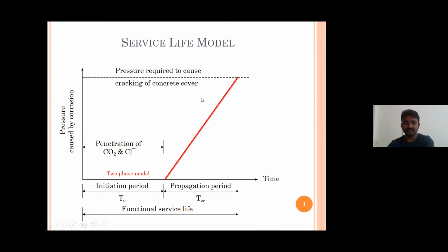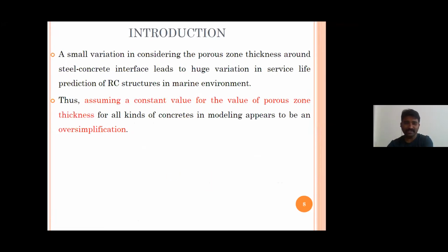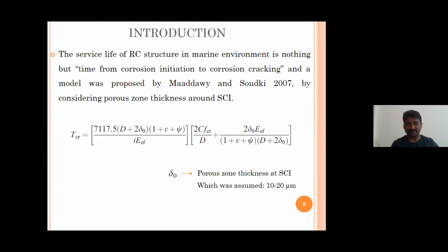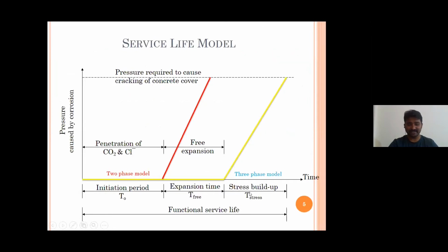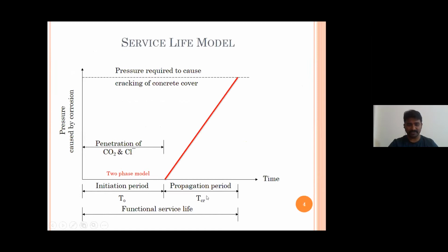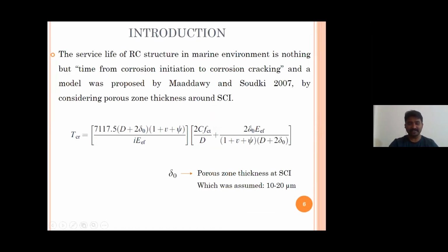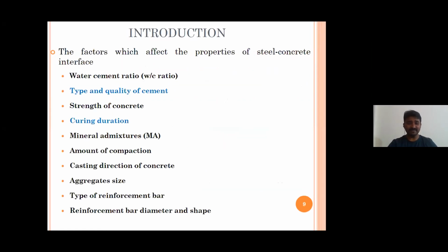What happens then? Once they start assuming the porous zone thickness, even a slight variation in the assumed porous zone thickness leads to huge variation in service life of structures. As you can see, Maaddawy and Soudki in 2007 proposed that the service life should be determined using this equation. As you can see, this is T_cr, the total propagation period. They divided the propagation period by considering this delta naught, that is the porous zone thickness at the steel-concrete interface. However, in this case also, they have assumed the porous zone thickness as 10 to 20 micrometers without any experimental validation or verification. In this present study, what we have done is we have experimentally tried to find out that porous zone thickness.